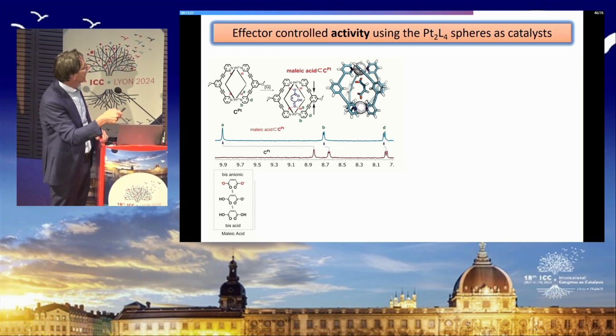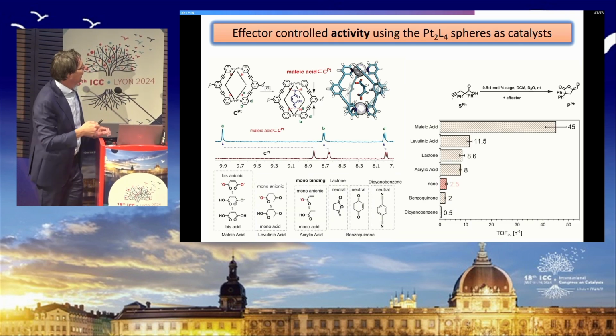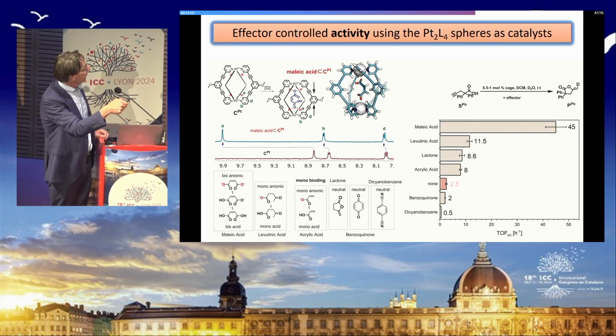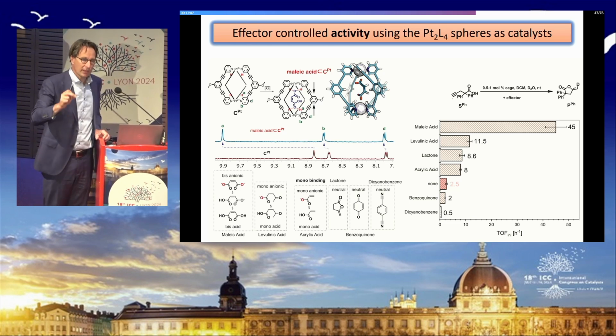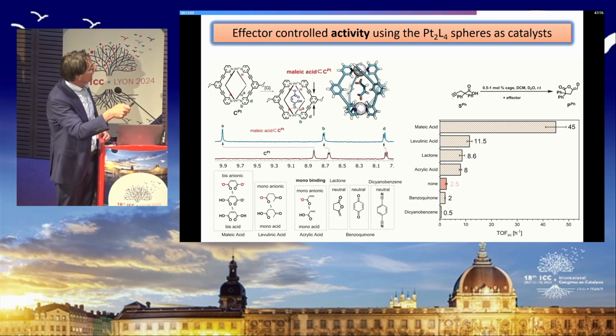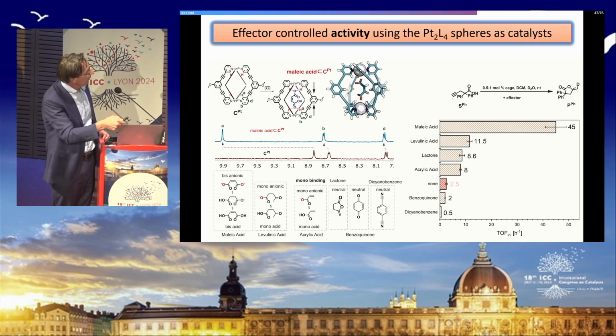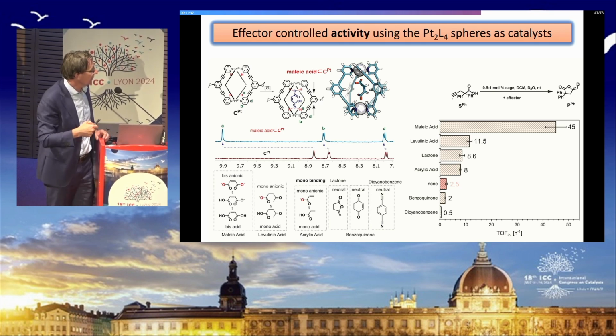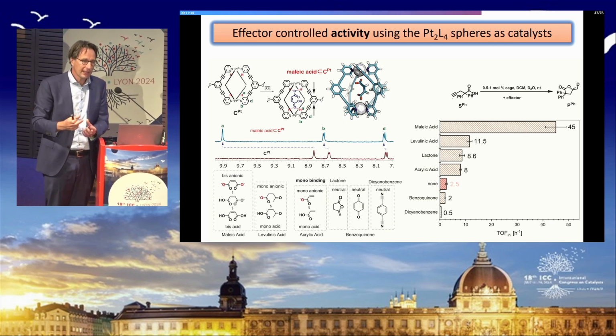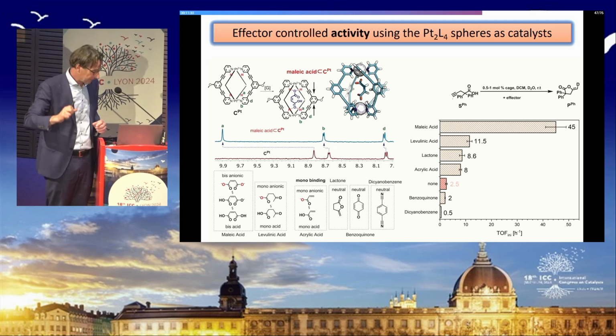So we looked at these maleic acids in diprotonated and diionic states, and we did all the binding studies, as you can see here, by NMR, and that's maybe a little bit too detailed, but we proved that they bind inside. And also we looked at all the other substrates that can bind inside, and after establishing that they bind inside, we used them as effectors to change the reactivity of the platinum. And again, we probed the cyclization reaction. What we found is that if you have no effector inside, then we have this reactivity of 2.5, and then we can upregulate by adding these type of monoacids up to a factor of 45, and we can also downregulate by adding this benzoquinone and this dicyanobenzene. So we have a molecular cage in which we can control the reactivity by the effector that we bind inside.